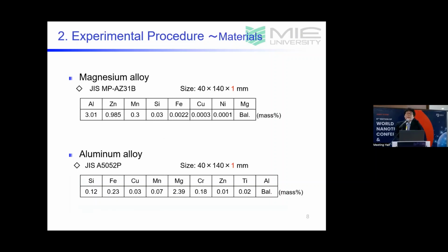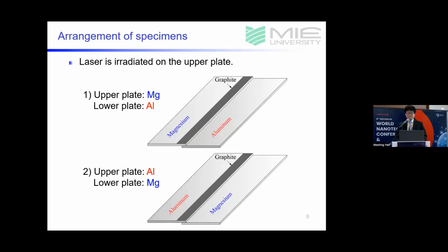For the materials, magnesium alloy sheet, AZ31B, and aluminum alloy sheet, A5052P, were used. The thickness of both sheets was 1 millimeter. This table shows the chemical compositions of materials used. These figures show arrangements of specimens in laser roll welding. In this experiment, two types of arrangement were examined because the laser is irradiated on only the upper plate. One is the upper plate of magnesium alloy and the lower plate of aluminum alloy. The other is the upper plate of aluminum alloy and the lower plate of magnesium alloy.